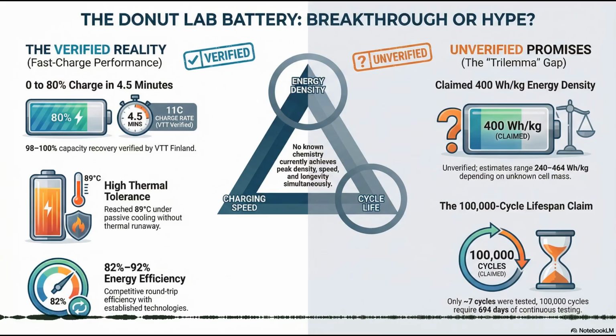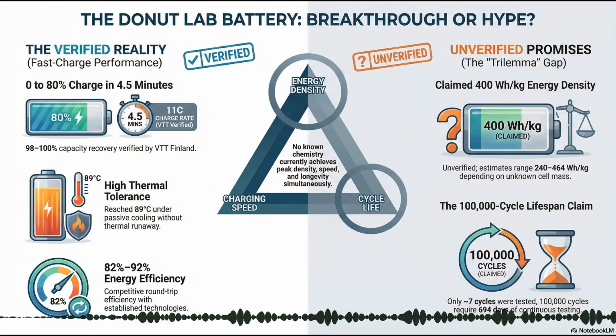And scenario C, just a conventional liquid lithium-ion baseline. Standard liquid electrolyte cells with copper current collectors on the anode and graphite are usually around 2.6 to 2.8 grams per cc. That would yield about 250 Wh/kg. So for the 400 Wh/kg claim to be true, it basically has to be a lightweight cell architecture. No heavy steel casing, no thick oxide ceramics, maybe not even standard copper foils. Exactly. It points heavily toward a polymer-based or a sulfide composite system.